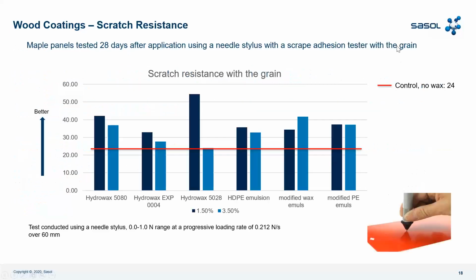So the first result shows the scratch resistance with the grain. We used a maple panel tested 28 days after the application, using a needle stylus with a scrape adhesion tester with the grain. You can see here the control, meaning without wax, gives a result of 24 in the test. You need to read the test as: the highest value is better.